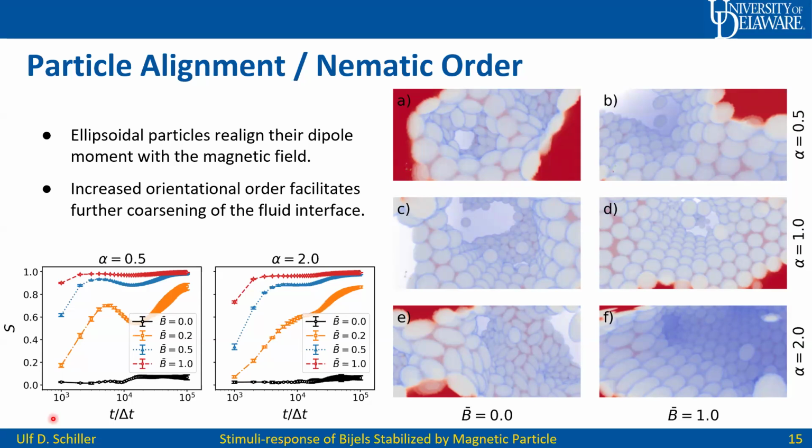Do you see particles extruded from the interface, or do they remain there? Another great question. Occasionally we see particles being expelled from the interface, because the compression in the interface is not small. It typically happens during pinch-off events or coalescence, when the largest rearrangements happen. Occasionally a particle is pushed out of the interface and then may remain, but it's very few, like 1% or so.